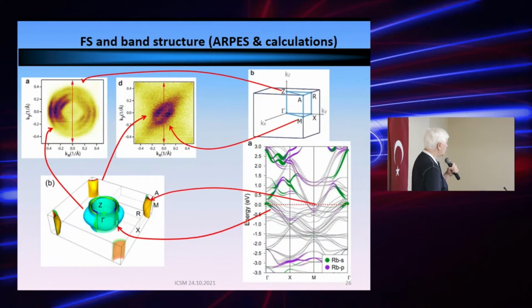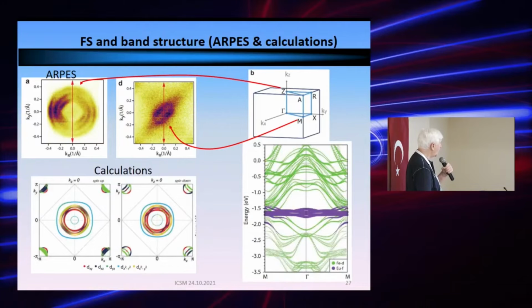Okay, now this picture of the band structure I already showed you, and I want to understand where the energy levels are located, those levels which are responsible for the magnetic ordering, so the europium levels. For this we have to move to lower energy, and we indeed find a bunch of levels located at about minus 1.8 electron volts below the Fermi energy. So here are the levels responsible for the superconductivity, and these are clearly for magnetic ordering.